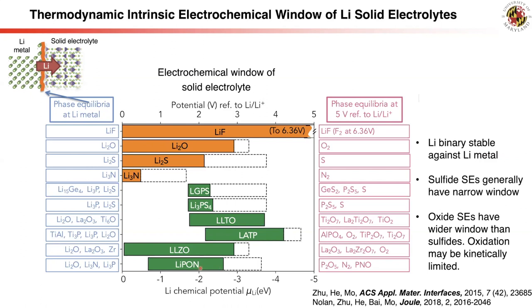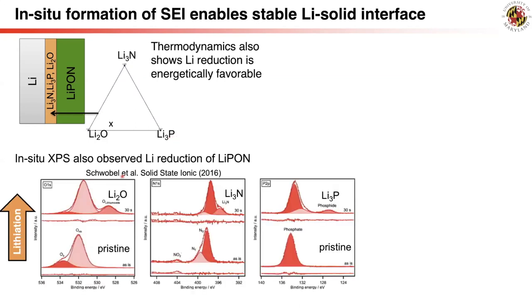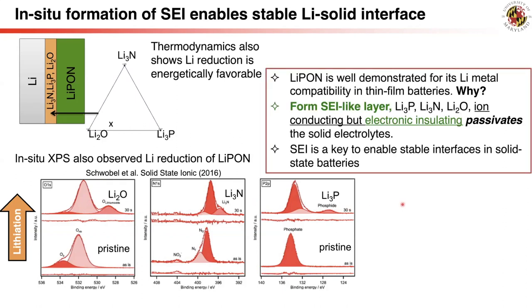LIPON is a well-known solid electrolyte that works very well with lithium metal anode in thin-film solid-state batteries, while thermodynamics shows it is unstable with lithium metal. Thermodynamics show that LIPON's phase equilibrium with lithium metal produces lithium nitride, lithium oxide, and lithium phosphide, and in-situ XPS characterization also confirms formation of these phases at the lithium-LIPON interface. LIPON works well because these reaction products are lithium-ion conducting but electron insulating, forming a solid electrolyte interface between lithium metal and LIPON that passivates the solid electrolyte and prevents further reactions. This SEI formation is similar to SEI formation on graphite anode in lithium-ion batteries using liquid electrolyte.